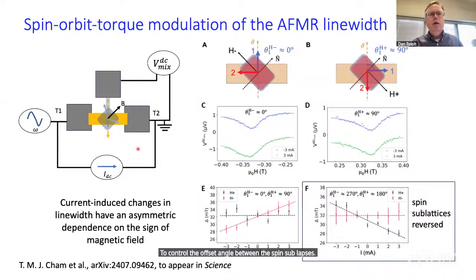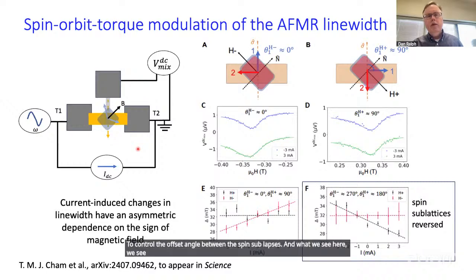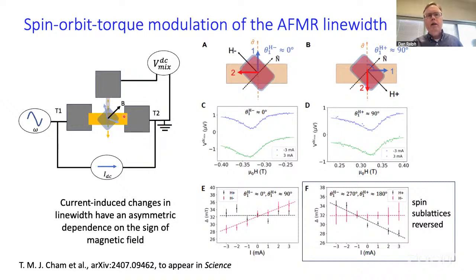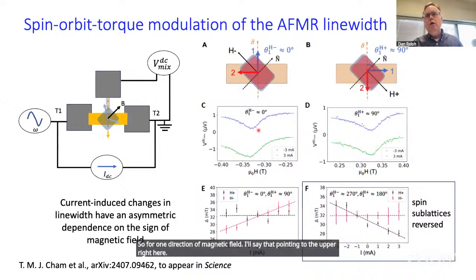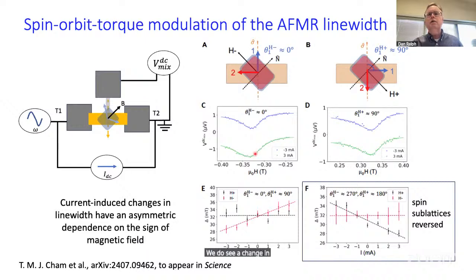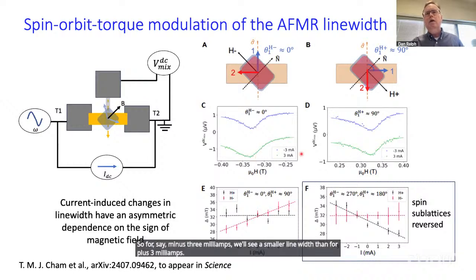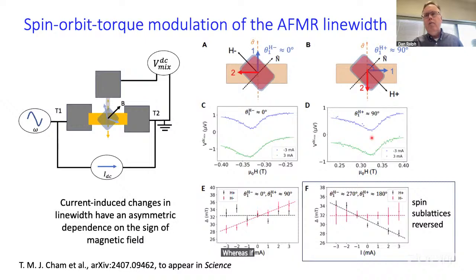And what we see here are different changes in the line width as a function of current, depending on what direction we apply the magnetic field. So for one direction of magnetic field, say pointing to the upper right here, we do see a change in the line width as a function of current. For say -3 milliamps, we see a smaller line width than for +3 milliamps. Whereas if we apply the magnetic field in the opposite direction, along the lower left here, there's essentially no effect of the current on the line.